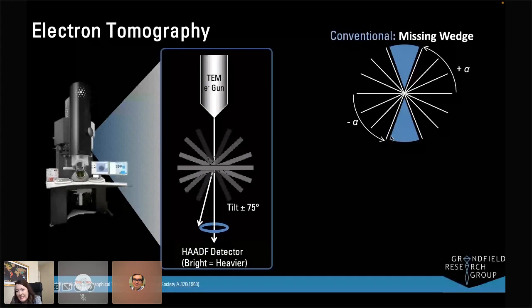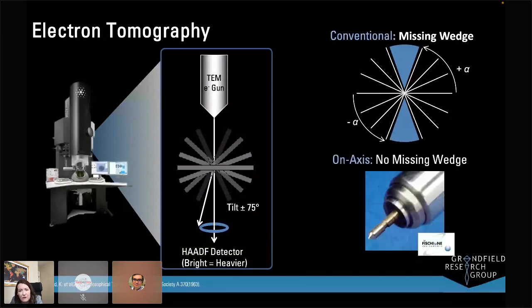So ideally, we'd like to rotate a perfect 360 degrees, and we can do that by performing something called on-axis electron tomography. And in this case, instead of having a thin, flat sample like I showed you, we make a thin cylindrical sample, which we can rotate inside of the microscope.